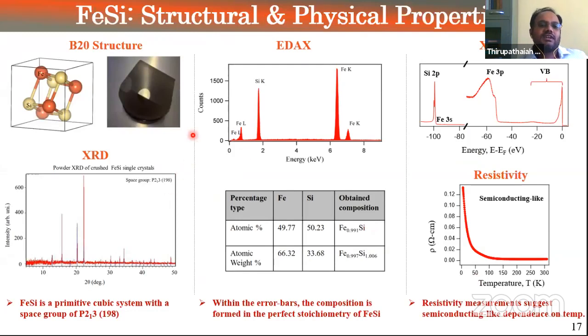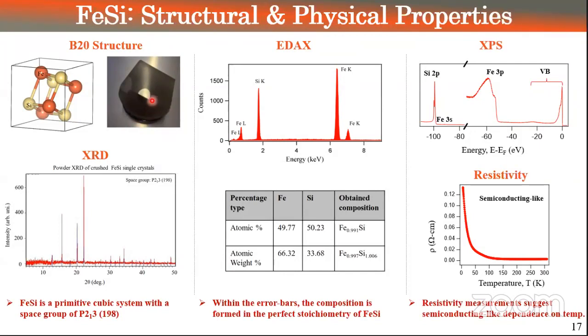So this iron silicide, or all these cobalt silicide, rhodium silicide, are B20 type structure. B20 in the sense that the unit cell is cubic, but with reduced symmetry. It has no inversion symmetry and also no fourfold rotational symmetry. And this is basically the crystal that we measured. In fact, the crystal was very hard, so the crystal grower needed to use a diamond cutter to cut it.